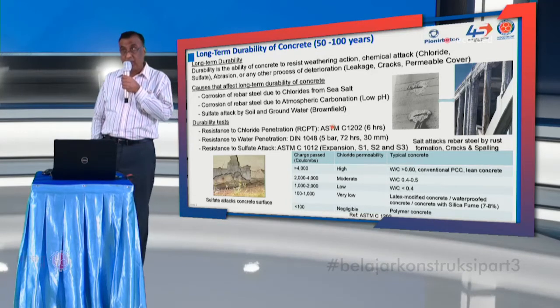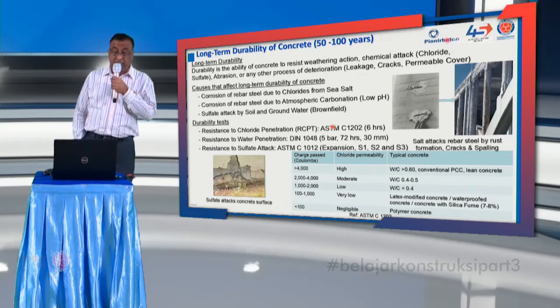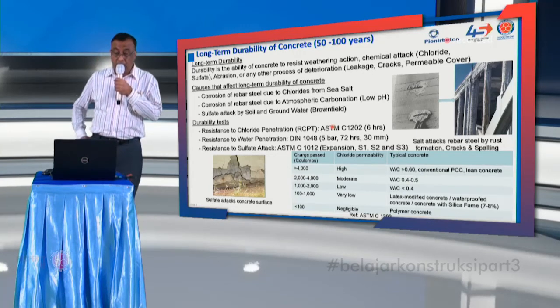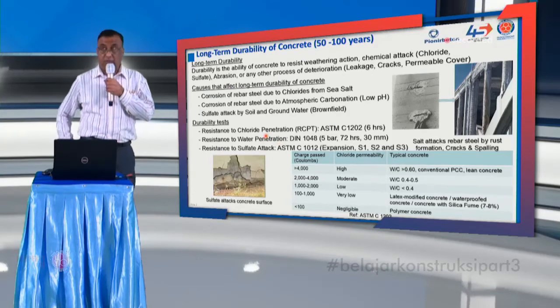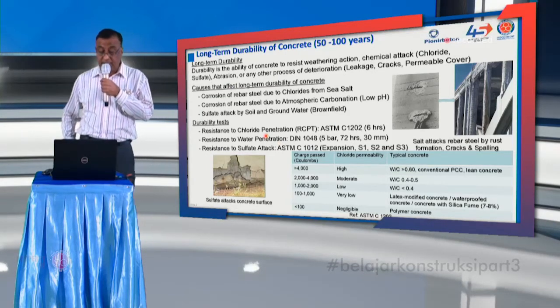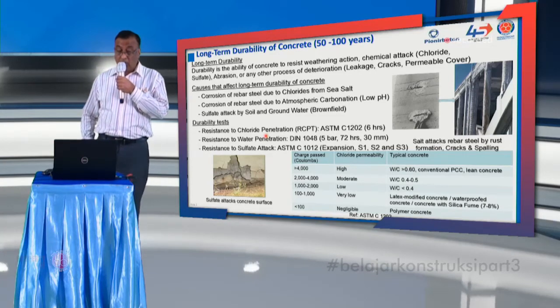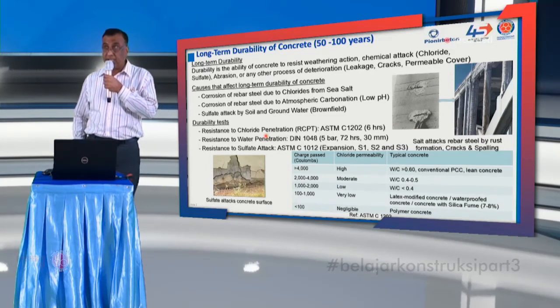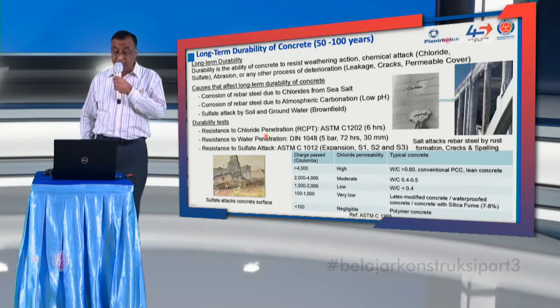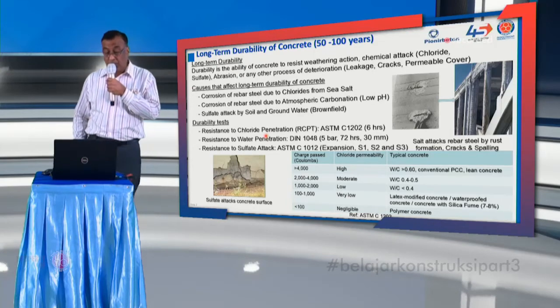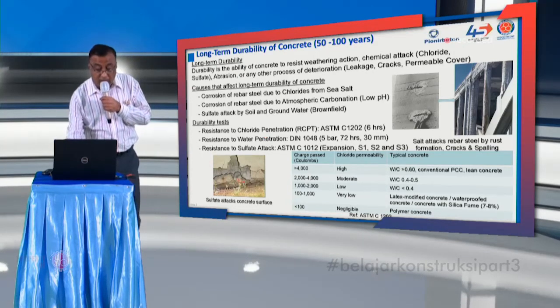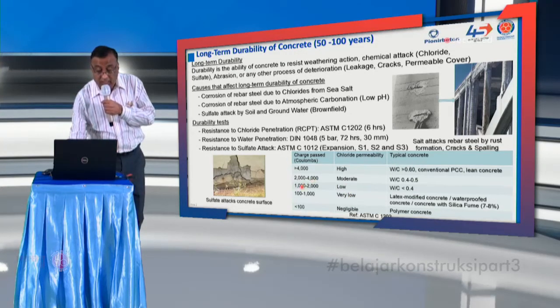This is a difference. So when you have this kind of aggressive environment, we do three kinds of tests here. You can see here, for chloride penetration, we do RCPT based on the ASTM standard 1202, and for water penetration, we do based on the German standard DIN 1048, and the sulfate resistance based on ASTM 1012. Most of the people in industry, they will ask for RCPT, and they'll ask very low chloride permeability, somewhere around 1,000 to 2,000 coulombs, or 100 to 1,000 coulombs. That's what most of the people ask. I have pointed out here. This is the range you have to get your permeability.